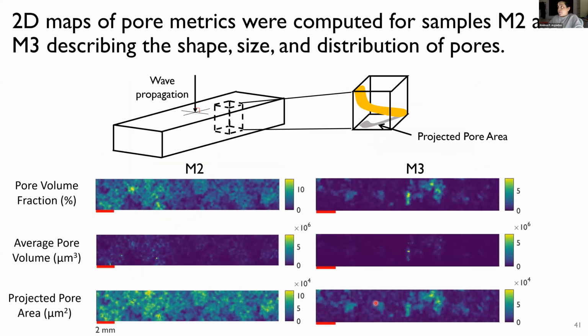Now, if we look at the regions where the porosity was high, we needed to essentially convert our three-dimensional X-ray CT data into a 2D map. So we went with a couple different features that you could look at. We took a voxel of X-ray CT data and propagated that all the way through the thickness of the sample, since that's essentially what our ultrasound was doing. And in that little volume, we calculated the pore volume fraction, the average pore volume, and what we call the projected pore area.